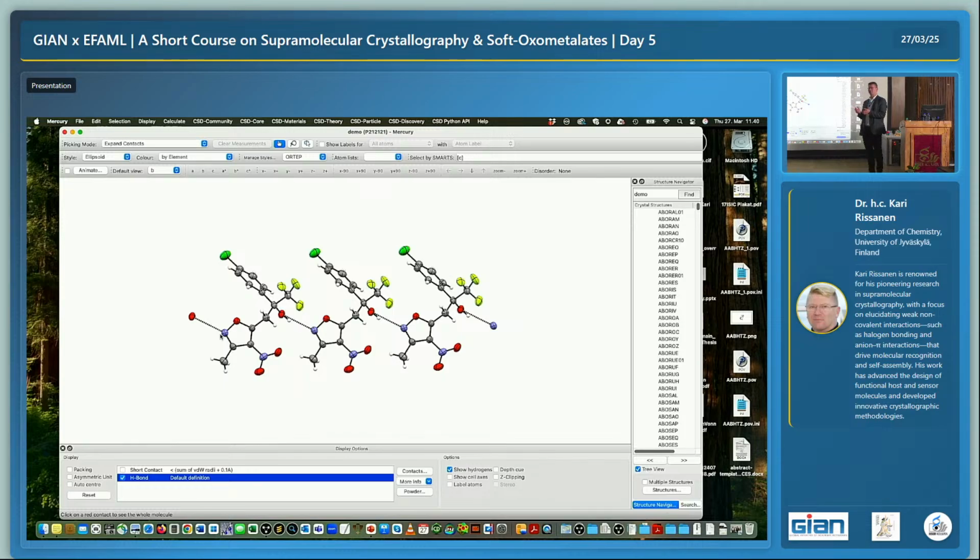How they are organized. And now this organization, if it changes slightly, but the components are the same, then we call it a polymorph. The different structure from the same molecule, different crystal structure. There might be 10 different crystal structures for the same molecule, because they come from different conditions. Remember, when we grow the crystals, we can change conditions. It might depend on the solvent condition, which kind of structure comes out, even from the same molecule.